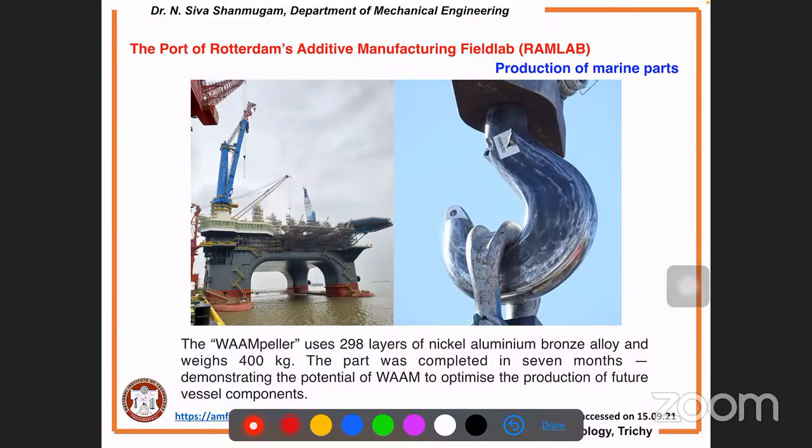I want to thank MX3D. From their website only, I gathered this information. So the Port of Rotterdam, it is in the Netherlands. Additive manufacturing field lab. They have erected the robot in the field for developing this component. So the crane hook, what is that material? Nickel aluminium bronze alloy, something around 400 kg. So 298 layers of nickel aluminium bronze, they have made one above the other